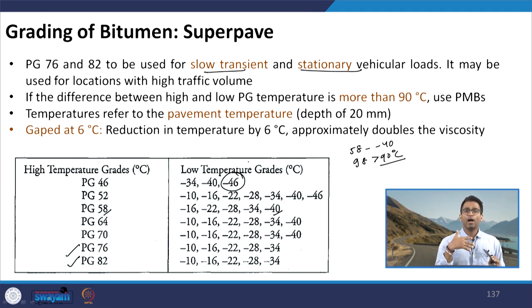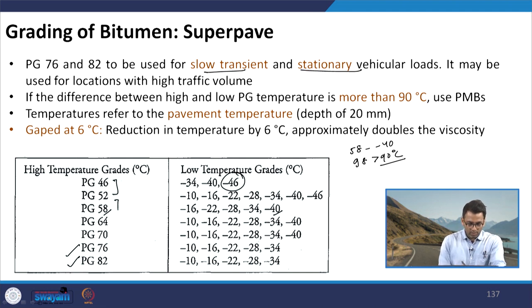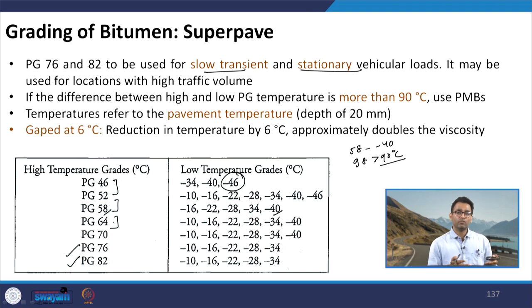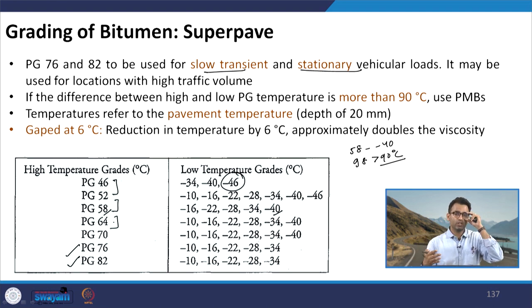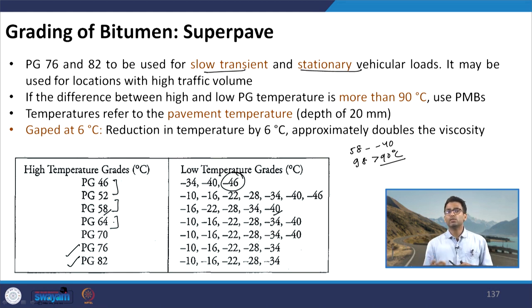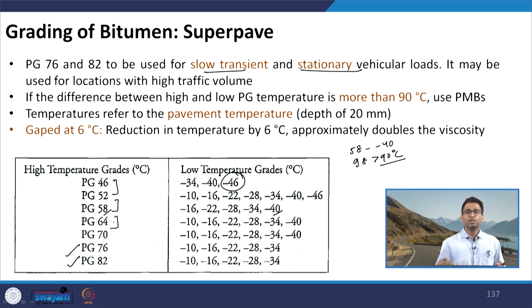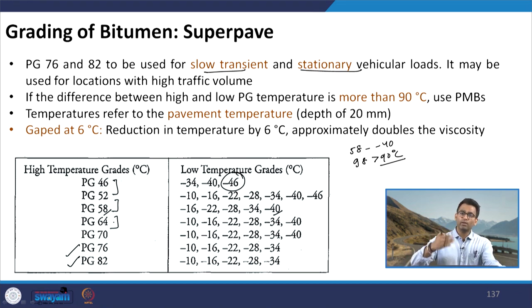On the high temperature side, based on air temperature they developed a correlation for pavement temperature, taking pavement temperature as higher than air temperature. Another important point: if you see the specification closely, the values are gapped at 6°C — there is no grade like PG 47, 48, or 50. The reason is that grading at every 1°C is not practical due to significant overlap between binders. They found that a reduction of 6°C approximately doubles the viscosity of the binder, making it easy to differentiate between grades.